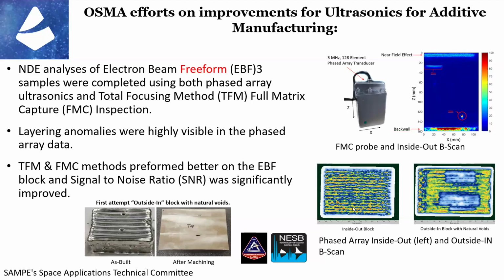But especially pre-heat treatment, what we found with these blocks is that you tend to get, at least in the phased array, these kind of regions where we're actually seeing layers and the grain structure show up as noise that is on the level of what a 1/8 inch flat bottom hole would be. The TFM system and the full matrix capture tended to do a little bit better, mostly because we could post-process out a lot of this work here.